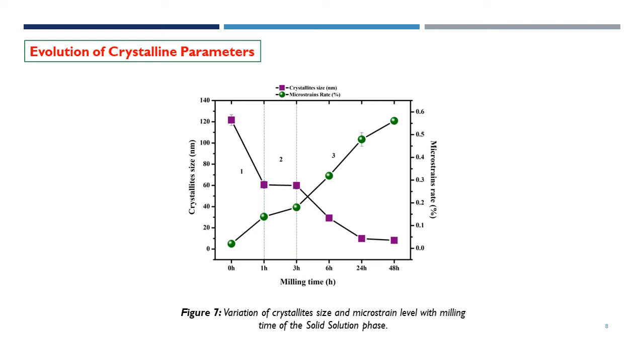In fact, this increment of strain is mainly due to the large density of dislocations generated by the severe plastic deformation of highly active nanoparticles that exhibit an anisotropic behavior. The attained maximum strain level can be justified by the transition of the deformation process from plastic deformation via the formation and movement of dislocation to the sliding of the grain boundary.